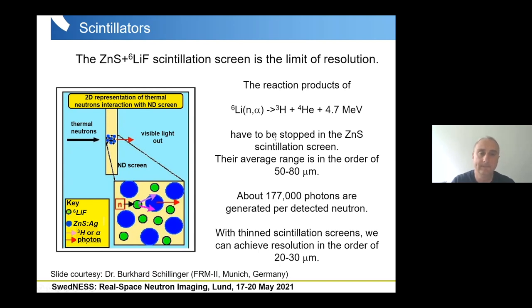So you can see here that the neutron is first absorbed in the 6 lithium fluoride, and then we have emission of triton and alpha particles. And this secondary radiation, the triton and the alpha particles, are interacting with the scintillating material, and then visible light is produced. So the photon, which is produced here, we can detect by our camera.